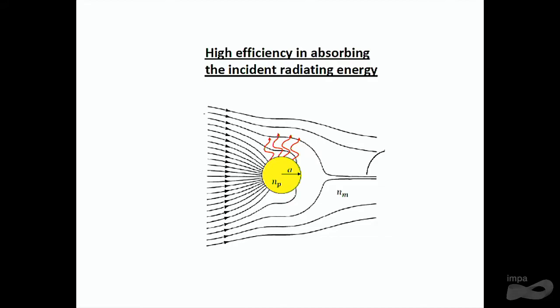So if you have a gold nanoparticle, that's what's going to happen with the field lines of the electric field. They are going to converge into the particle, and the particle is going to be very efficient in absorbing light. So if you put a small amount of particles in a matrix, let's say in this case a polymer matrix, those particles are going to take most of the incident light, and you don't need to put many particles. So you have this advantage.